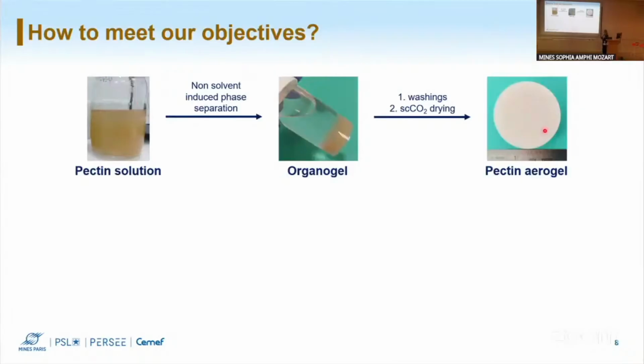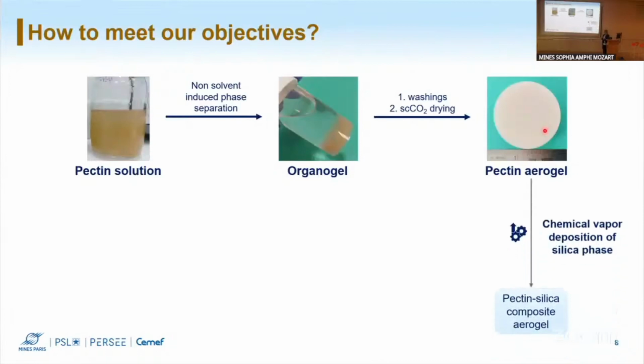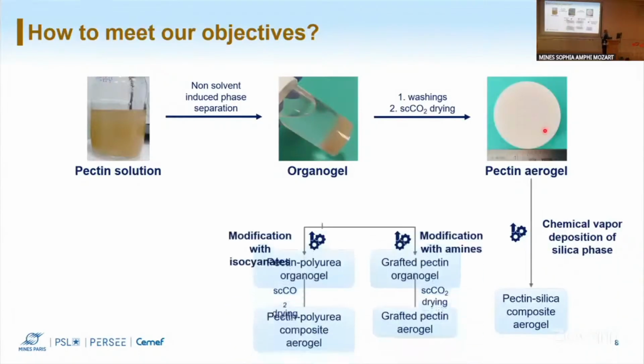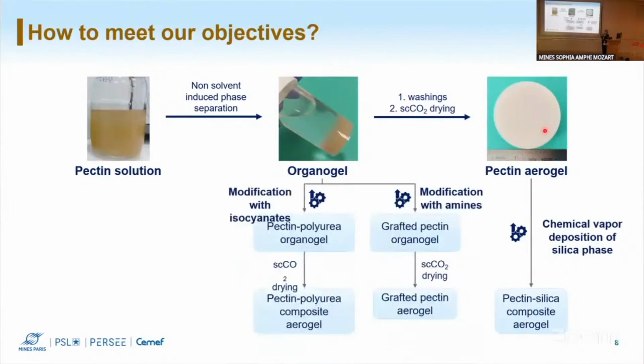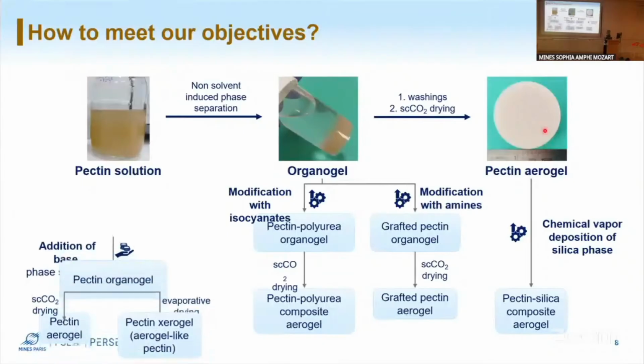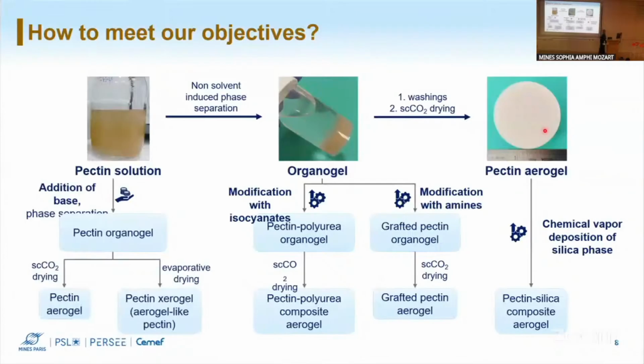We had different approaches, so we could work on all the different steps of the synthesis. We tried to work with the dry aerogel, and in this case, we performed chemical vapor deposition of a silica phase. Then we worked on the organogel phase so that we can keep the structure after coagulation and obtain the superinsulating properties, and we did modification with isocyanates and modification with amines. And we also worked on the pectin solution in order to optimize the process to avoid supercritical drying, by doing the coagulation in alkaline media.